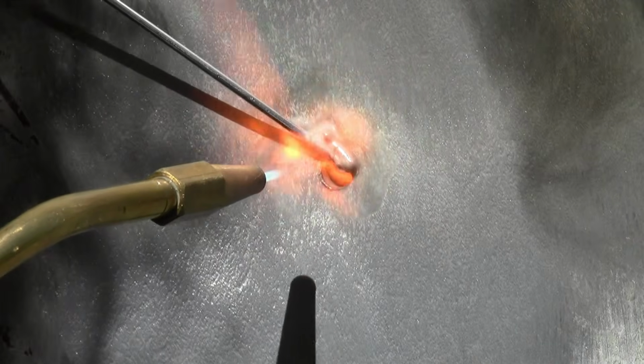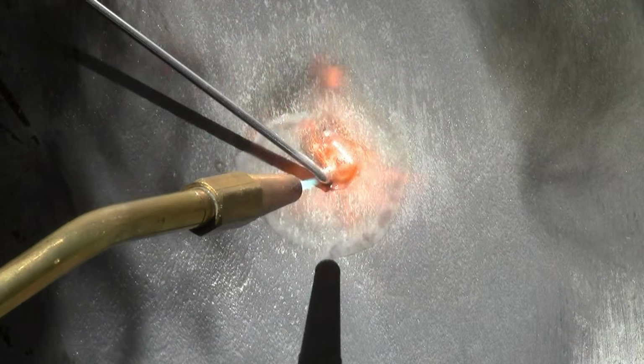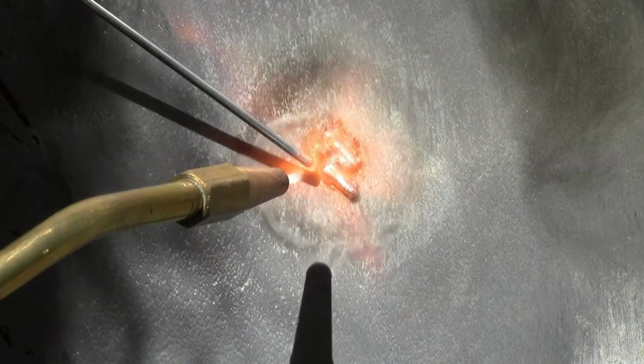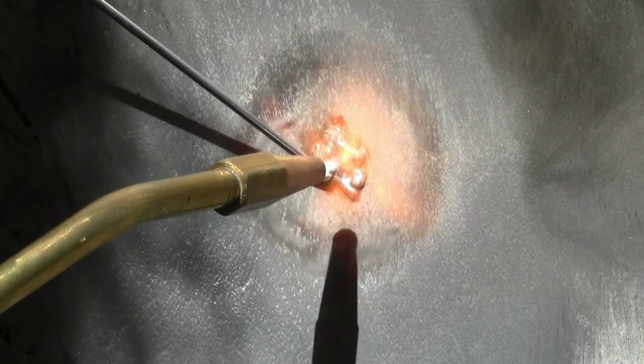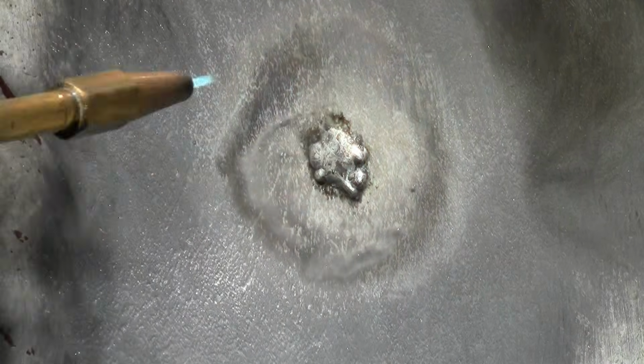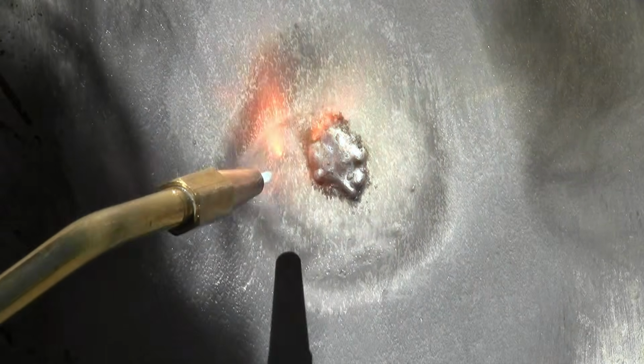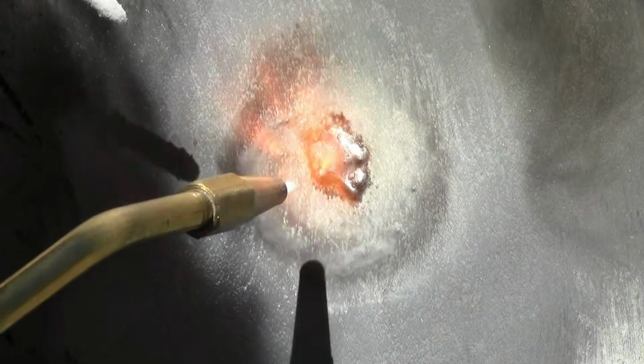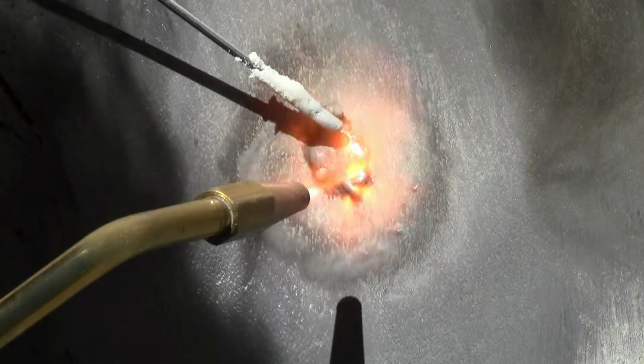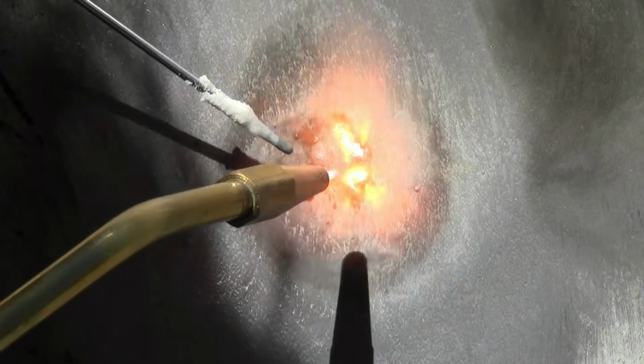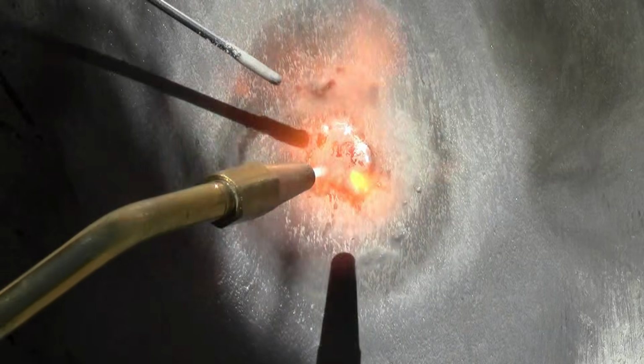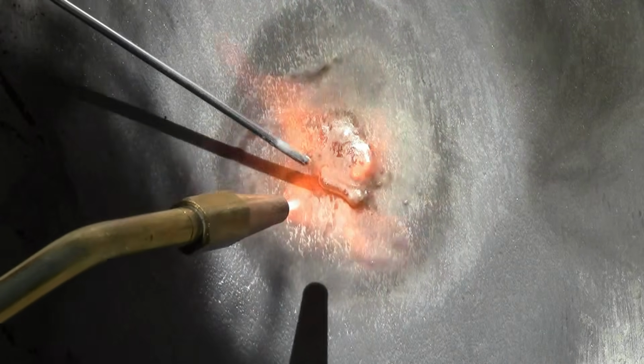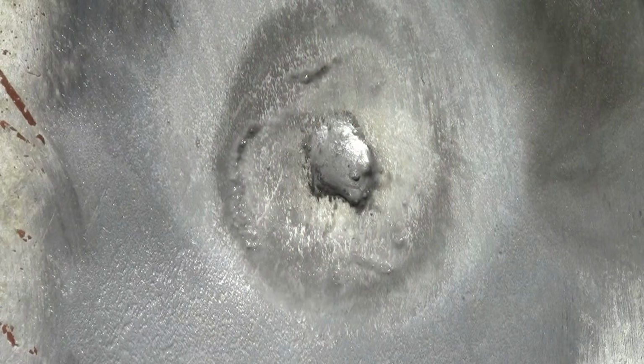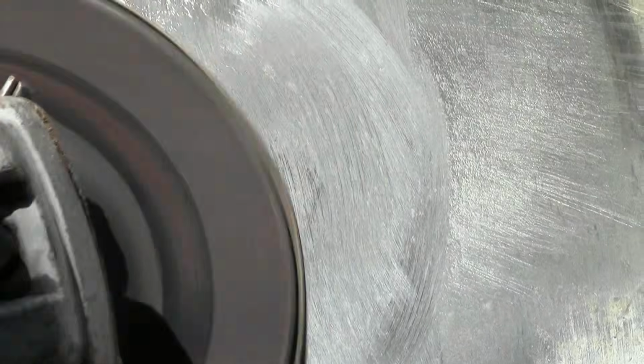Then we practically paint the hole shut. So if you were brazing on a crack and accidentally blew a hole from keeping your torch in the same spot for too long, you see how easy it would be to fix your mistake. After we close a sizable leak, we add more flux to solidify all the deposits together. Remember, our flux is what allows us to have an airtight, watertight seal. After removing the flux with warm water and a wire brush, we sand it down and look forward to another day on the water.